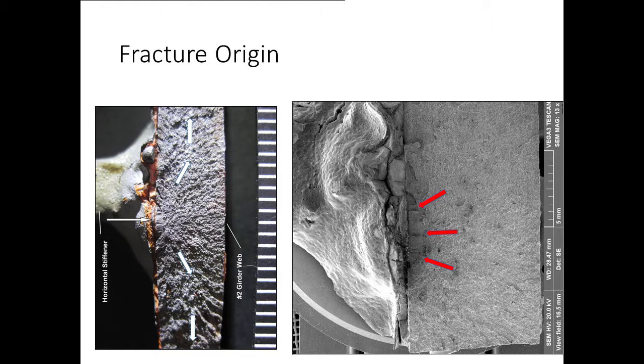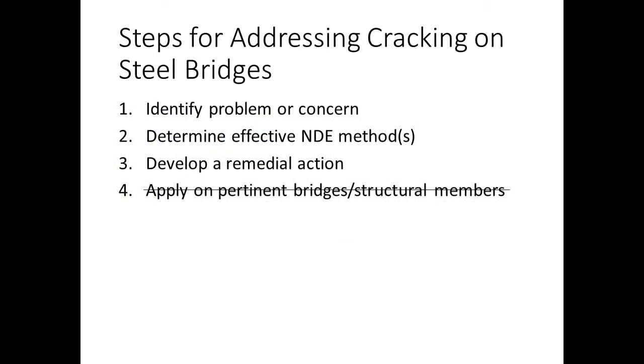And despite its small size, we knew within an inch or two where the crack would occur, and we went to the Cabinet and said, well, we can take a die grinder and clean this area up and come in with eddy current and detect it. And if you don't want to do that, you can put check holes above and below the horizontal stiffener. Again, we had a problem. We had what we thought was an effective non-destructive evaluation method, and we also had a remedial action. What did the Cabinet do? Well, the Cabinet did neither. What they did do is frequent visual inspections of the problem areas, and then the Division of Maintenance sought to expedite replacement of these two bridges because they're six-laning I-75 near there, and they wanted to replace the bridges with up-to-date structures rather than do expensive repairs.